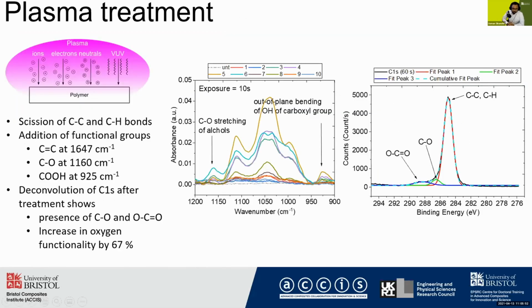So what plasma treatment does is when it interacts with the polyethylene, it basically breaks the carbon-to-carbon bonds in the main chain and also the pendant groups. And these are the sites where the functional groups that come from the plasma jet stream attach to the surface. So as a result of plasma treatment, we can see that there is formation of carbon double bonds and attachment of oxygen at different wave numbers as seen by the FTIR data.